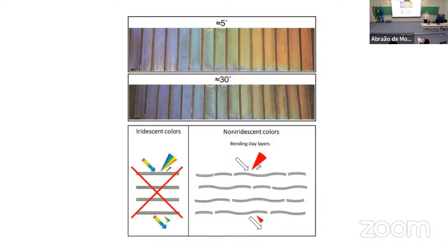If these were completely flat and stiff, you would get angle-dependent color very sharply. So you have to look at different angles, you will see a different color. In our system, no, because of this.